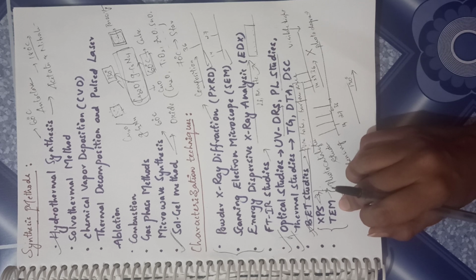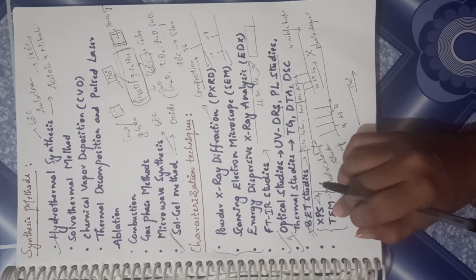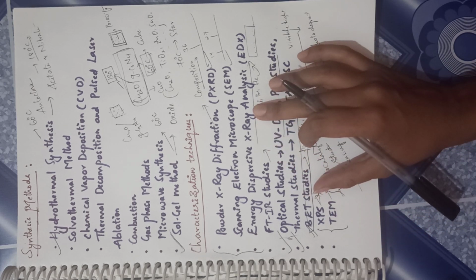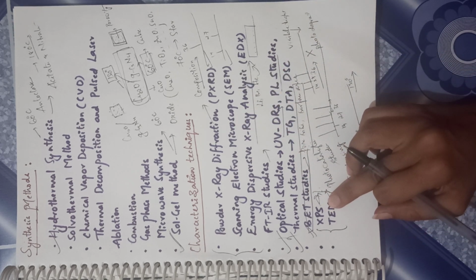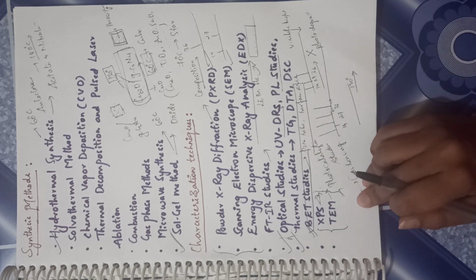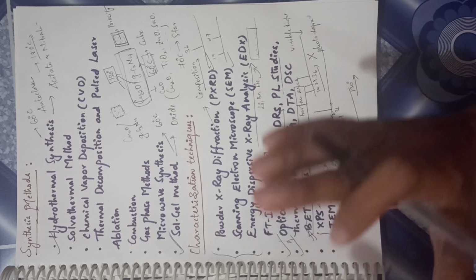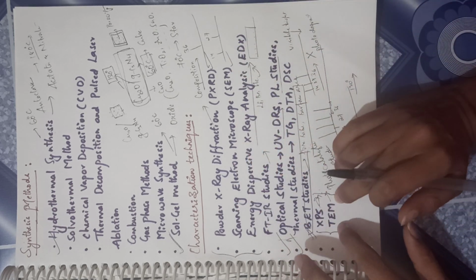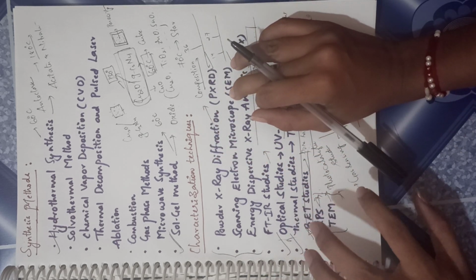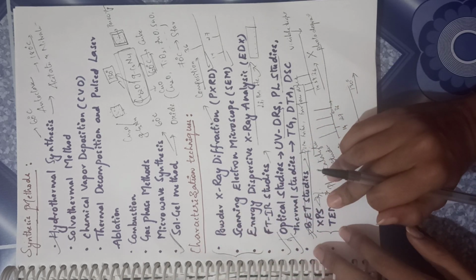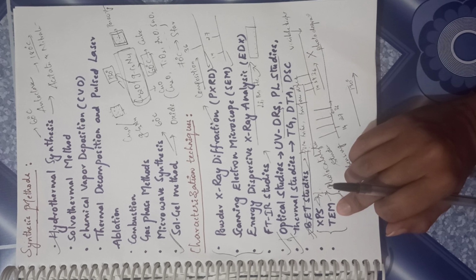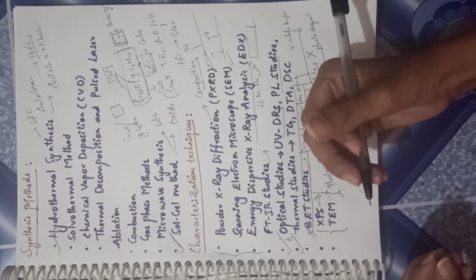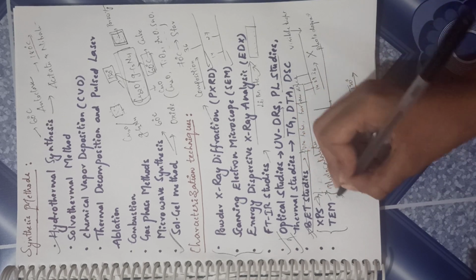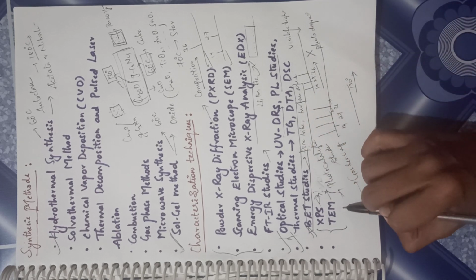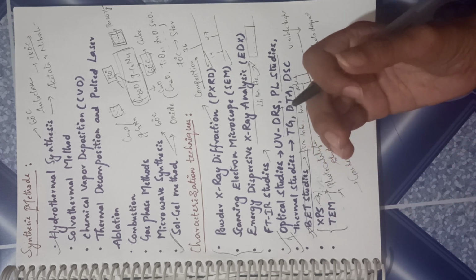followed by TEM. Now TEM is transmission electron microscopy. SEM and TEM, what is the difference? SEM creates an image by detecting reflected or knocked off electrons, whereas in TEM, the transmitted electrons which are passing through the sample create the image. So TEM offers valuable information on the inner structure of the sample, such as crystal structure and morphology, which is not the same with SEM. SEM gives only the surface morphology and surface information, whereas from TEM the inner crystal structure can also be determined. It is a very well-known technique for finding out particle size; nearly 1 nanometer can be detected using TEM. So TEM can be used to determine the particle if the size of the particle is almost less than 2 nanometers.